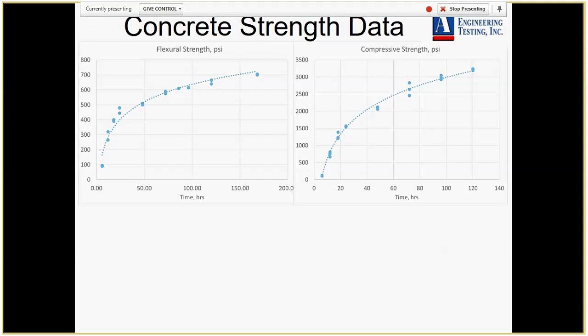But under this project, we reviewed the data provided to us from MnROAD, collected by MnROAD engineers and technicians, and tested by MnROAD or by consultants, like in this case American Engineering Testing. And this slide shows the testing of the mix used in construction prior to concrete placement. In this case, you see that the concrete flexural strength actually accelerates much faster than concrete compressive strength. And that is quite